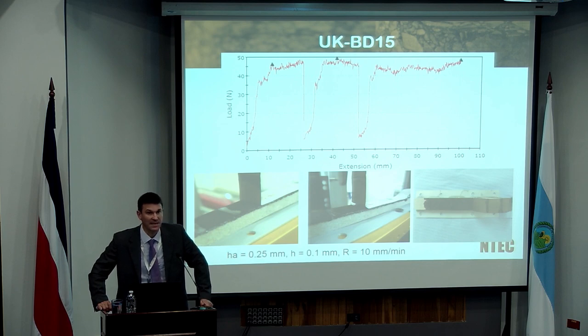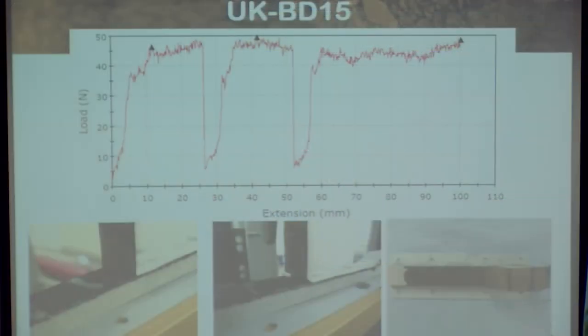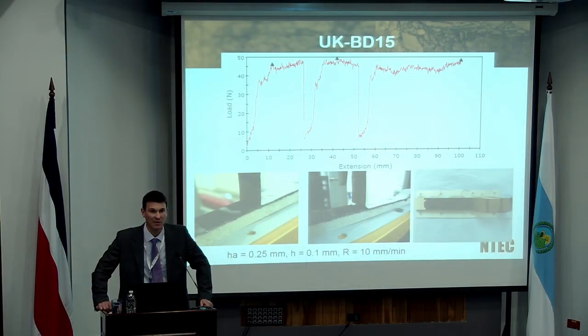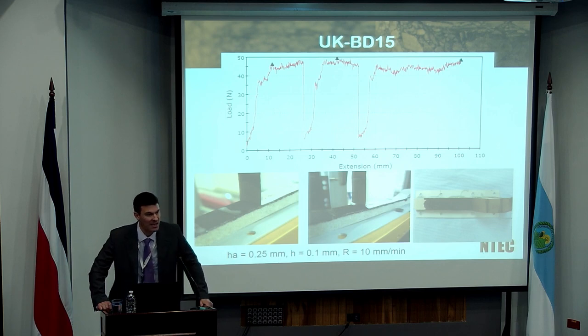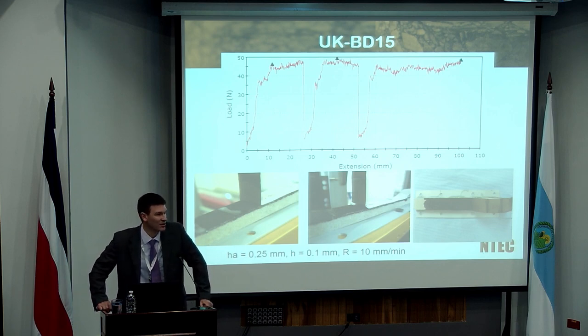So this is 15 pen. This is a very, very hard binder. This is the binder that you would typically use if you were producing a high modulus asphalt material, a major structural asphalt layer in your road. So a 15 pen binder, again using exactly the same displacement rate of 10 millimeters per minute, and again measuring the load. And the first thing to notice is that we now see that there are discontinuities in the actual results. And this is the effect of what we call crack jumping.